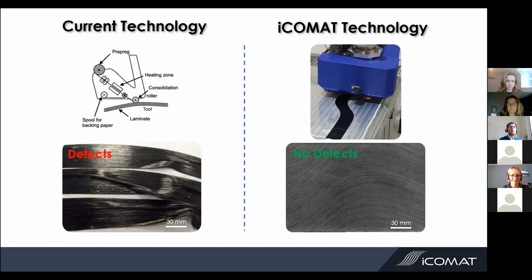Current technology, so I mean AFP and ATL, so automated fiber placement and automated tape laying machines, are the state of the art, and they're really good at placing fibers quickly in straight lines. They're great at that. However, if we want to utilize the benefits of curved fibers that I just showed you before, they're not so great at that. So the way they do it, these machines are normally robot mounted or gantry mounted, and the way they steer is they rotate the placement head to steer the fibers, but this causes bending in the tapes. And with bending comes defects such as wrinkling or buckling, which really have an important knockdown on structural performance.